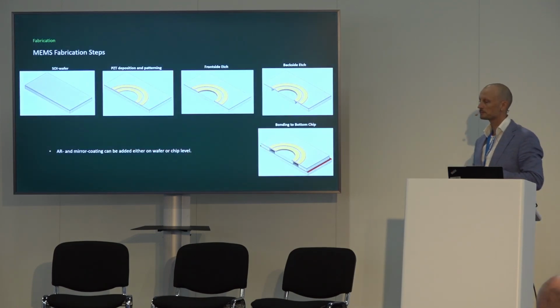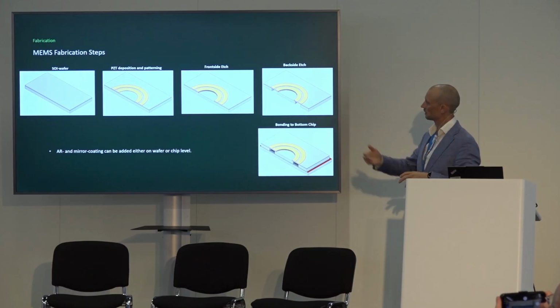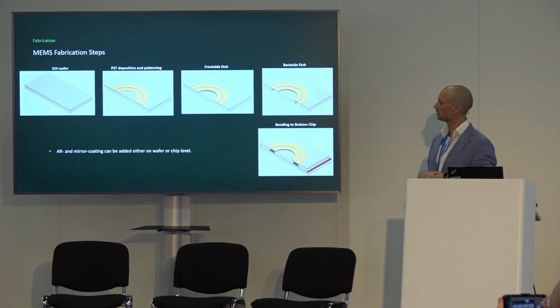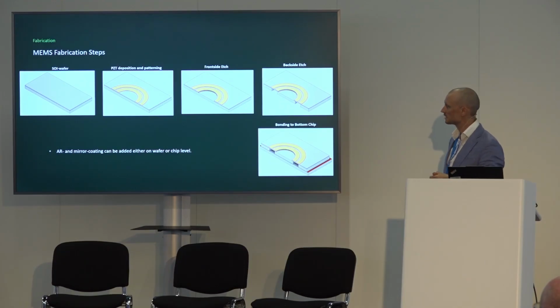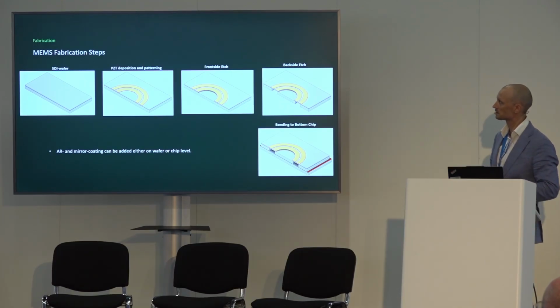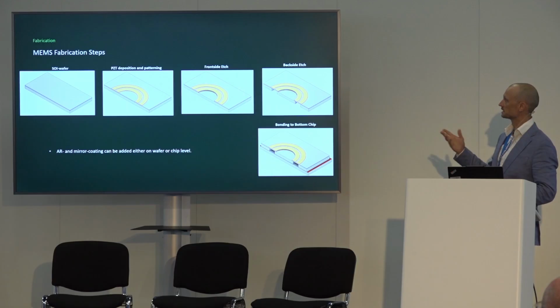That top chip is made like you see here. It's made on wafer level using semiconductor fabrication techniques, or MEMS techniques. So starting with a silicon on insulator wafer, we deposit PZT, pattern that, we do front-side etch, and we do back-side etch to release the piston.